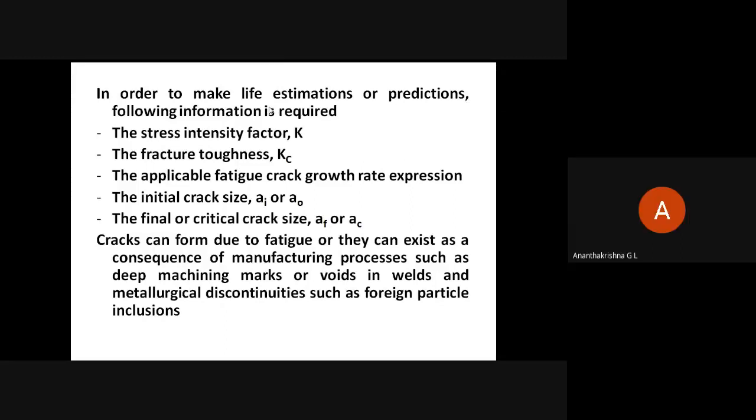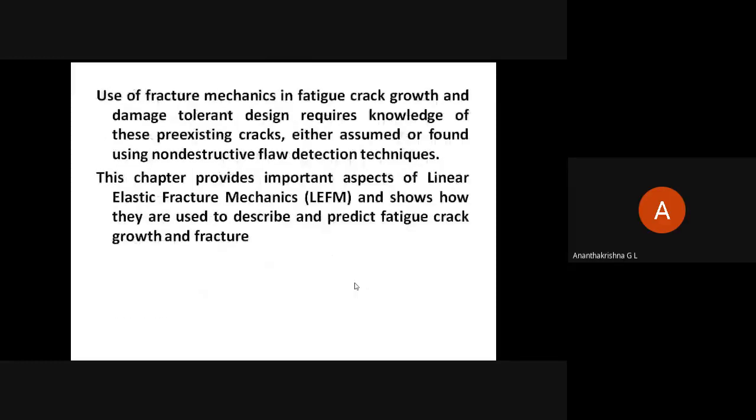So these are the five informations that are required to estimate or predict the life using fracture mechanics theory, which presumes the presence of crack. So cracks can come because of inclusions, voids, manufacturing processes, and so on. Next, use of fracture mechanics in fatigue crack growth requires knowledge of these pre-existing cracks, either assumed or found using non-destructive flaw detection techniques. So that is using X-ray technique or whatever, which is a non-destructive testing method.